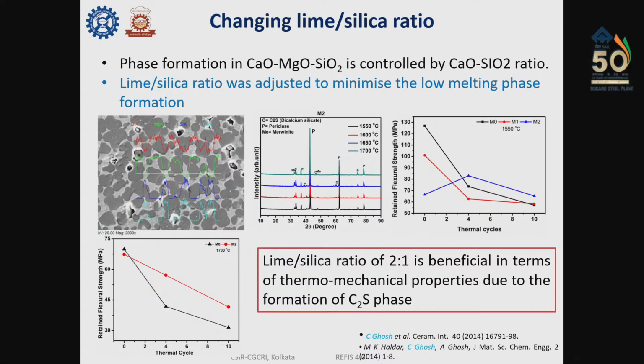In the first approach, we adjust the lime silica ratio and we have found that when the lime silica ratio is 2:1, it is beneficial in terms of thermomechanical properties, because if you see the XRD phase diagram, it forms dicalcium silicate, which has a very high melting temperature of more than 2000 degrees centigrade. Along with those, some merwinite phase is also there, but formation of this C2S phase improves the property of Indian magnesite.